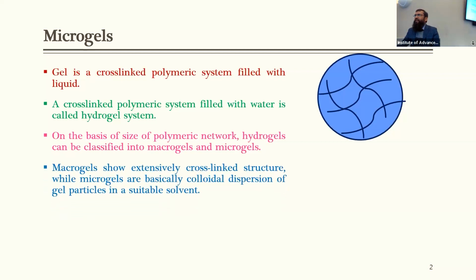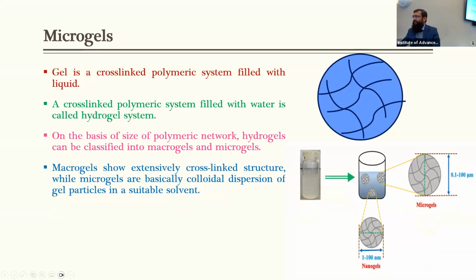Microgels, in fact, are a colloidal dispersion like this. We have cross-linked polymeric particles of colloidal size, which are dispersed in an aqueous medium. So the aqueous dispersion containing the polymeric particles is just like this. As a whole, this system is a sol because the solid particles are dispersed in liquid. But if we focus on a single particle, it is a gel system because liquid is entrapped in the polymeric network.